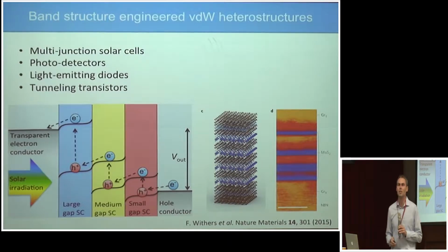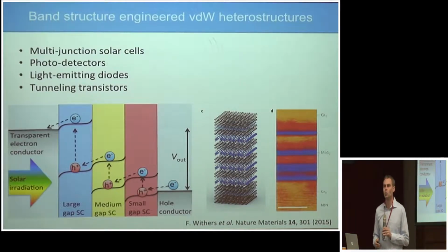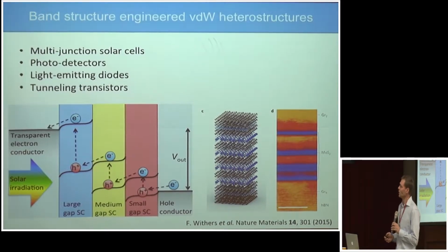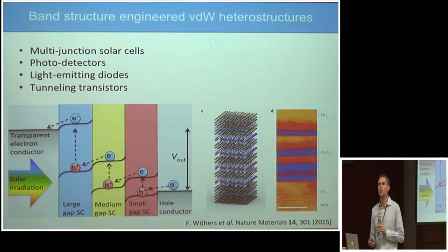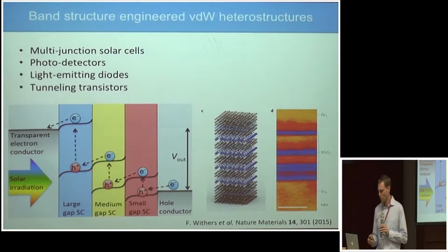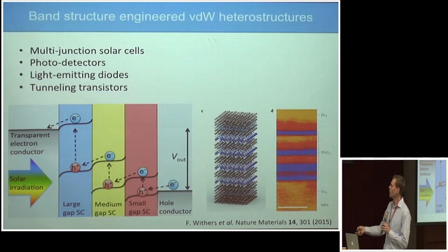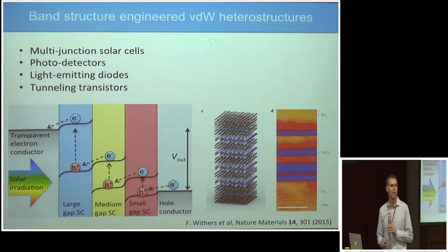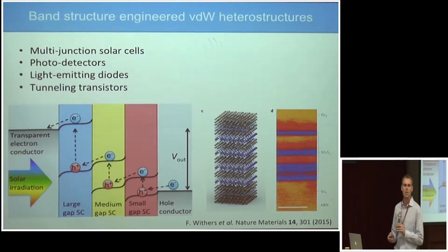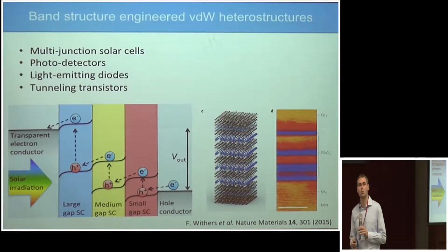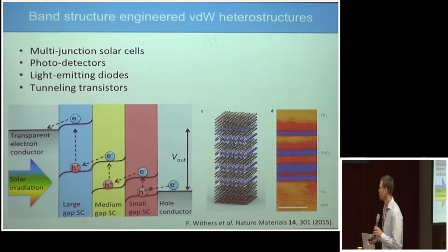I think today we can surely tell him what we would do if we were able to arrange the layers of materials atom by atom. So we would be able to make, for example, multi-junction solar cells with efficiency that significantly exceeds the Shockley-Queisser limit. Here's an example: by putting together 3 semiconductors with staggered band alignment and different band gaps, one can reach, theoretically, power conversion efficiencies reaching 70%.